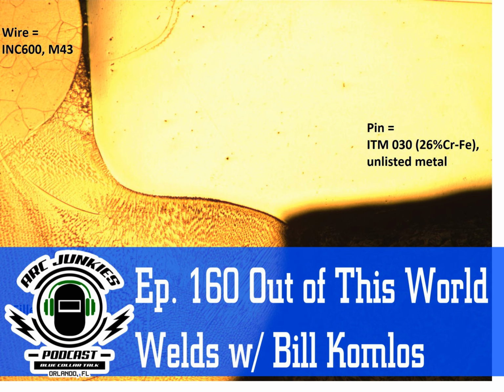We had offshore drilling rigs. Everything was big at CBI. I mean, 2 inches thick was nothing. And so you have to learn. They taught you these techniques, like when you're teaching in school. You take your 7018 test, you go side to side and pause, burn it in, and do your nice vertical up. Well, they taught us to fill 1-inch plate with 7018 in 3 passes. You weld a vert down 7018 in the back to hold the slag in.